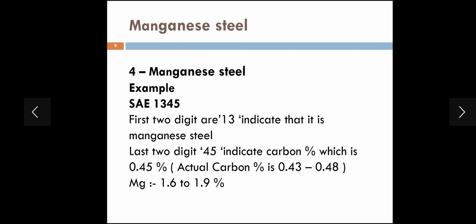Now, manganese steel. Manganese is also present in most of the steel up to 0.3%. If you add manganese in the steel, it promotes greater strength by increasing hardenability. So example of manganese steel is SAE 1345. So first digit 1, second digit 3, as per system, it is a manganese steel. And the last two digits 45 mean carbon percentage in the steel is 0.45%. Manganese present in the steel is 1.6 to 1.9%.